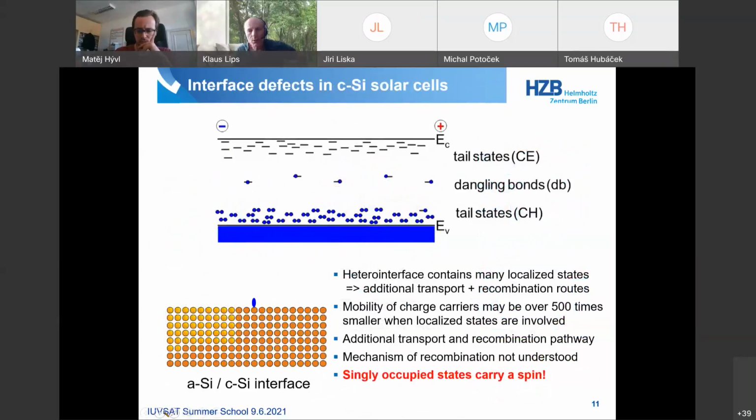And I will now show you what that does with respect to how charges behave in that material. Let's assume we have this perfect crystal here, and let's assume at that surface there is a single defect, a single ruptured bond. Let's assume there's no amorphous silicon on top. What is this now doing with respect to charge harvesting? Now, that forms a mid-gap state.